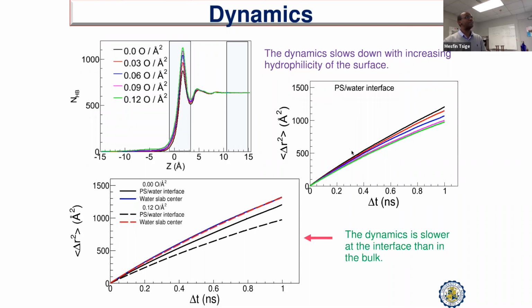We characterized the dynamics in terms of the mean square displacement of these water molecules as a function of time. This is for the case of no oxidation, and the green one is when the surface is fully oxidized. So there is a significant drop in terms of the dynamics of the water molecules.